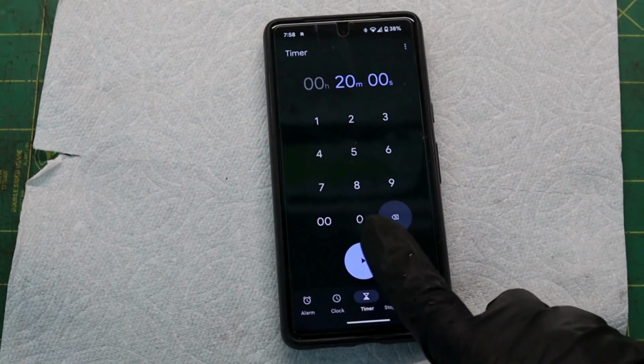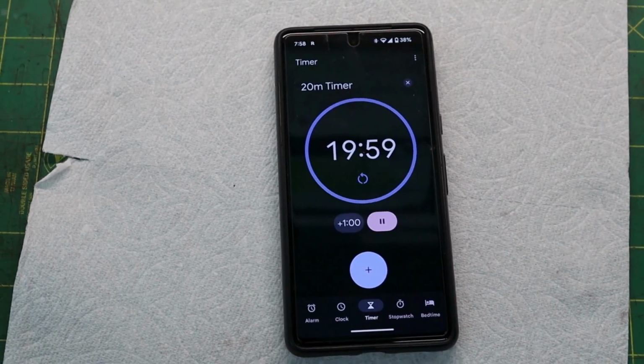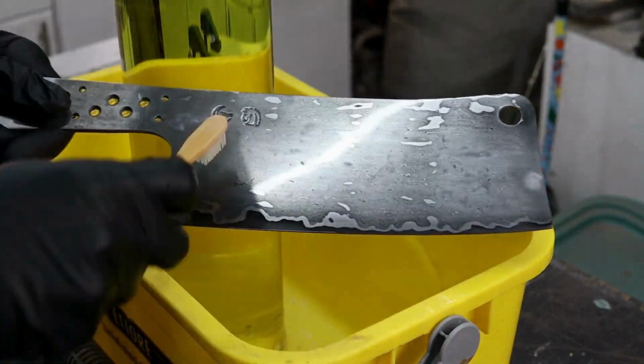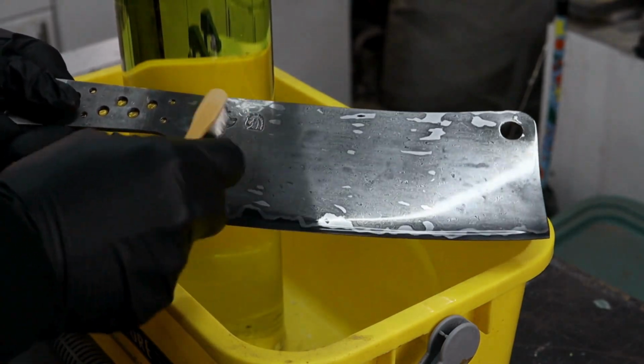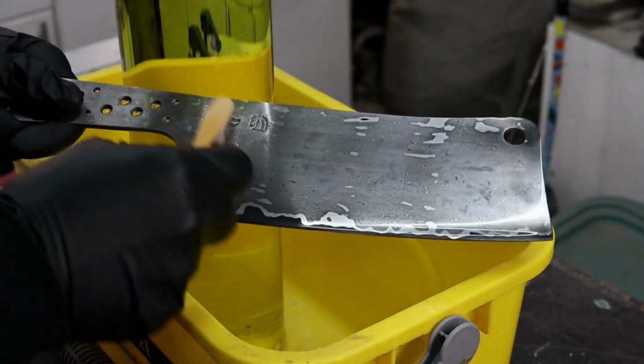I set a timer for 20 minutes and checked on the blade every few minutes during the etch. After a couple minutes, I noticed the pattern was a little funky near my maker's mark, so I pulled the blade out and brushed that area with a toothbrush before putting it back in the acid.